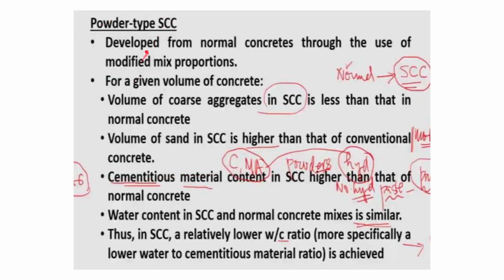So powder type SCC, if we see, is developed from normal concretes through the use of modified mix proportions. Okay, for a given volume of concrete, the volume of coarse aggregate in SCC is less than that in normal concrete.